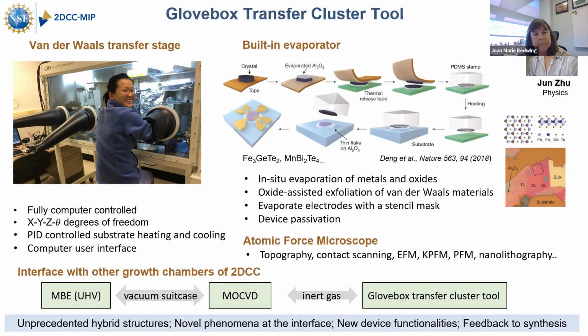And this process, this ability to transfer layers and do stacking, has enabled the formation of heterostructures and also twisted bilayers, which have their own unique properties. And based on input from users, we're setting up a specialized Glovebox cluster tool for layer transfer and stacking. And this tool, which Joan in the physics department has designed, will have a computer-controlled transfer stage that can manipulate the layer position and also the layer orientation.